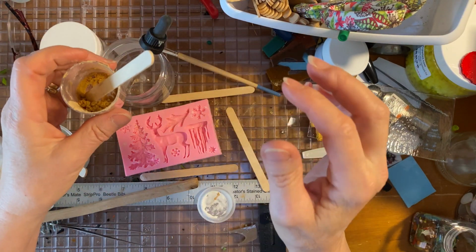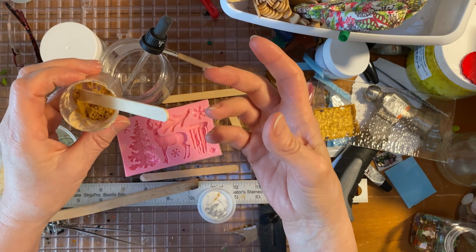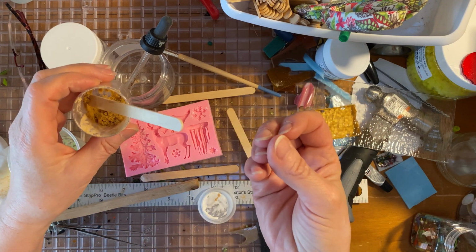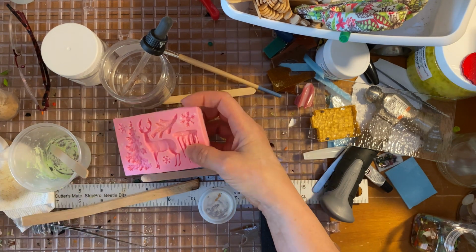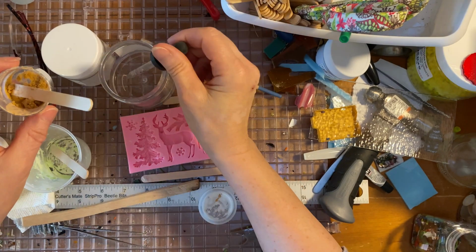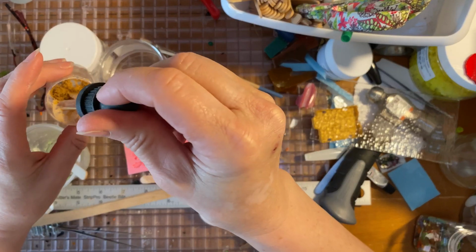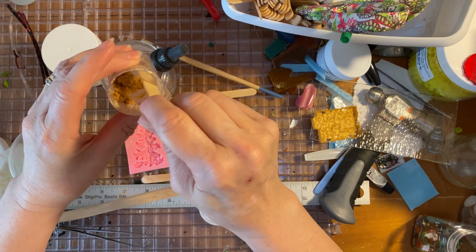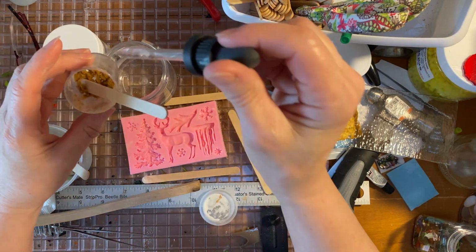You can't add so much water that the ratio is more water than glass, because then when the water evaporates and the piece fires, you won't actually have enough glass to hold together and fill in all these details. I use an eyedropper and put a few drops at a time. It takes a while to mix the right texture, but I find if you try to rush it and you don't get the right consistency, you get a failed piece, which takes a lot more time overall.